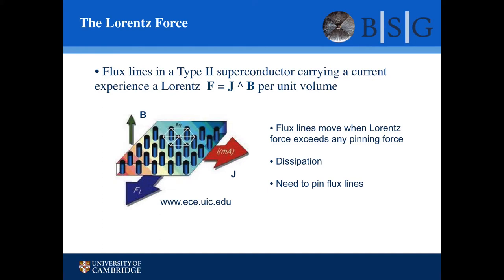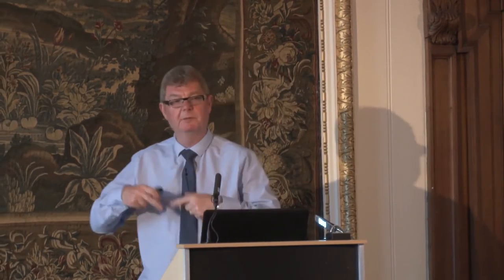So again, this is fairly schematic. If we now have a material carrying a current, so here's our superconductor with all its flux lines in there, and we're passing a current from left to right, we've got a magnetic field that's vertically oriented. Here we've got a cross product, and that just conserves the orthogonality or the 90 degree relationship between the variables. So J is at right angles to B. J cross B gives us a force on the flux lines, and that is at right angles to both J and B. So if we've got a B here, a J there, then we try to sweep the magnetic field lines through the material. If these are free to move, we've got a dΦ/dt again, a change in flux. Therefore, we've got an EMF. An EMF gives us a loss. Our material gets warm. If we're trying to keep it cold, then it becomes unstable.